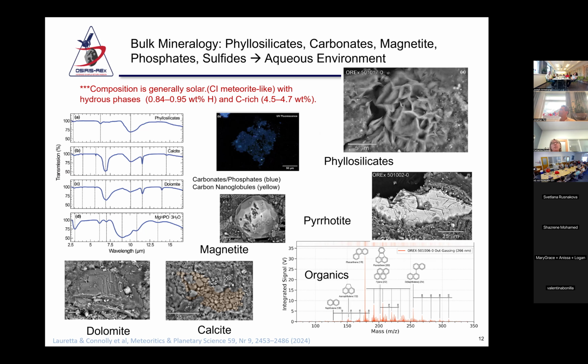There are hand samples. One of the first things that the team did was to try to compare these particular return samples from Bennu with our meteorite collection. We already knew from remote sensing that obviously it was carbonaceous, probably similar to a carbonaceous meteorite, but we didn't know which type. And actually, we originally thought it might be an ungrouped type of carbonaceous meteorite, like the Tagish Lake meteorite, which contains a little bit more carbon. In the end, these look very much like CI meteorites, which means that they have a composition that's generally solar, except for maybe the carbon, except for the organics and things that are very volatile. So we could use CI, depending on what you were thinking to do. CI meteorites would be the best analog and are very similar.